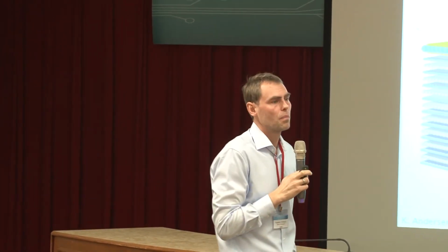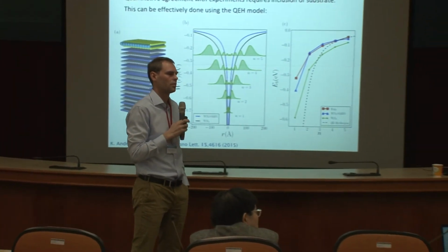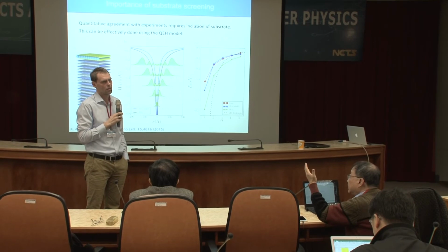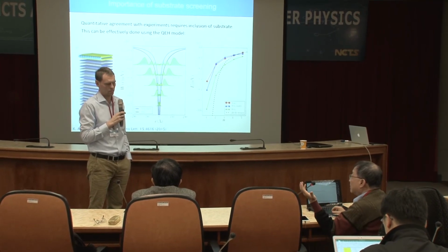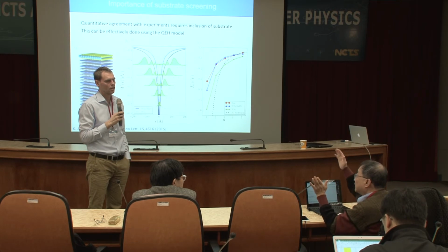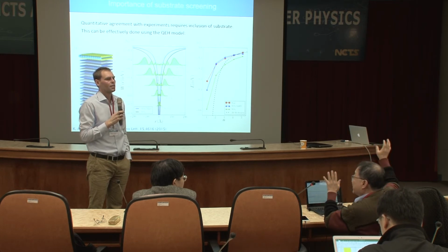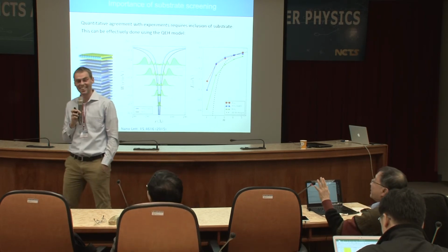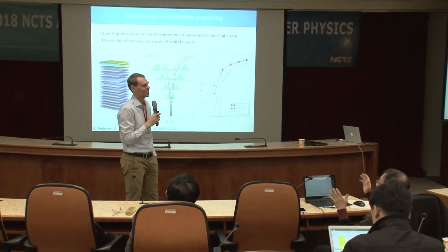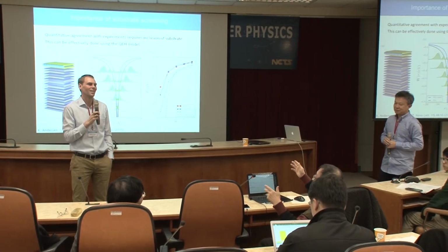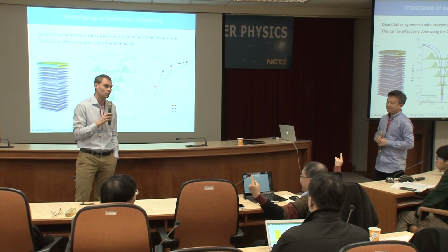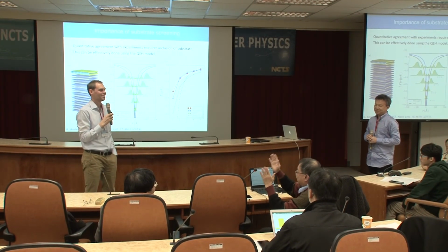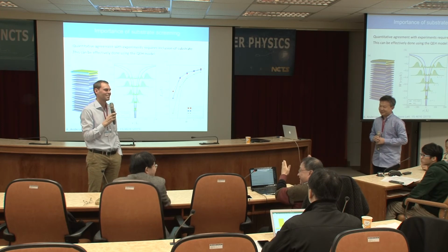Thanks. Yes. So, in your calculation of the quasi-particle band gap, that is still an isolated layer for MoS2, right? At the end, you see the quasi-particle band gap is 2.5, the exciton is 1.9. This quasi-particle band gap is kind of slowly creeping down compared to things done about 4 or 5 years ago. And as for the experiment, it's very interesting. At the beginning, all experiments showed exciton binding energies of 1 eV. And then experiments showed very large band gaps, and later on more and more experiments show smaller gaps than the calculation. That's true.